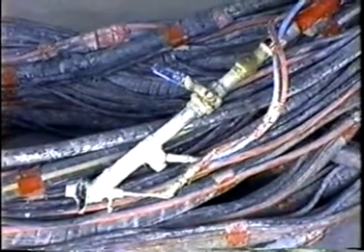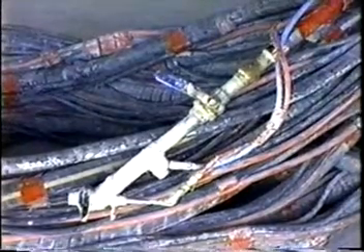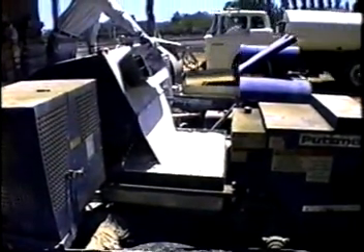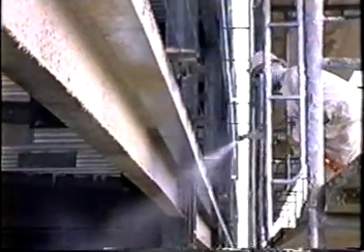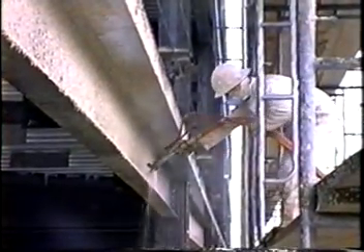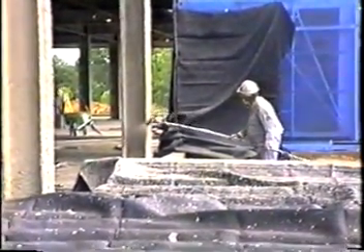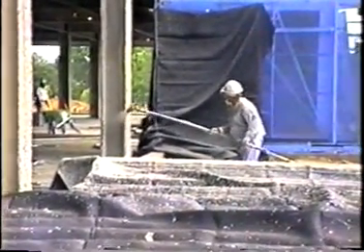For optimum coverage and density, a 5/8 inch inside diameter orifice is recommended. Once all the pumps and hoses have been primed with water at the start of the application, the material is then ready to be discharged from the mixer into the pump hopper. The material valve at the spray nozzle is then opened and the pump switch turned on. When the slurry begins to exit the nozzle, the atomized air should be adjusted to achieve a uniform spray pattern. It must be made sure that there is no restriction of material.